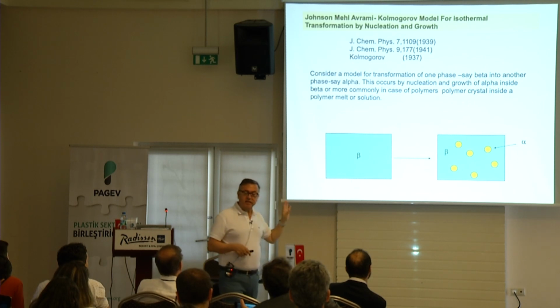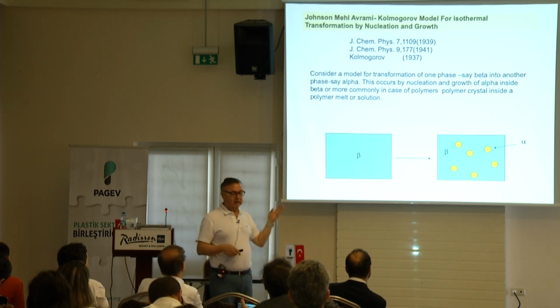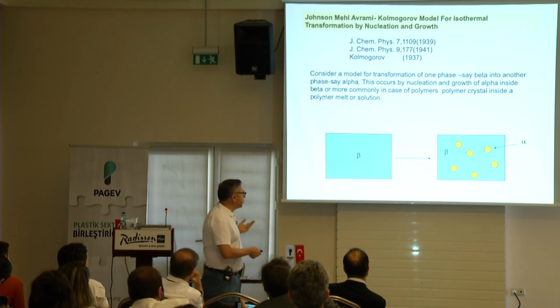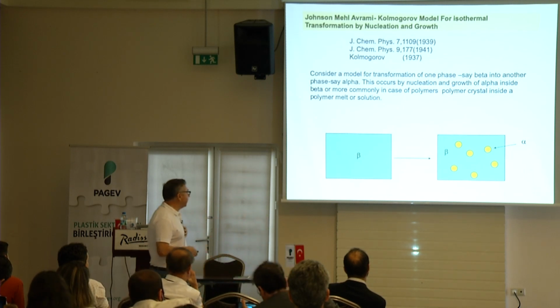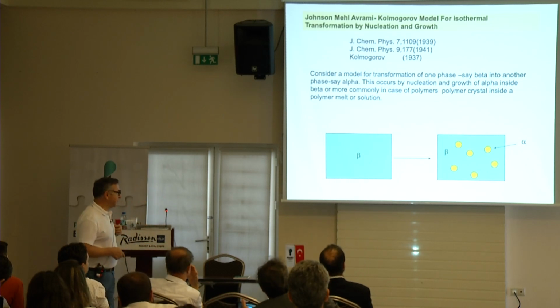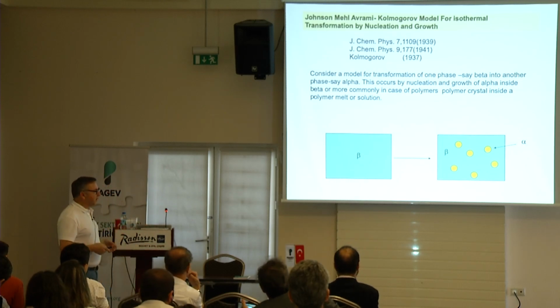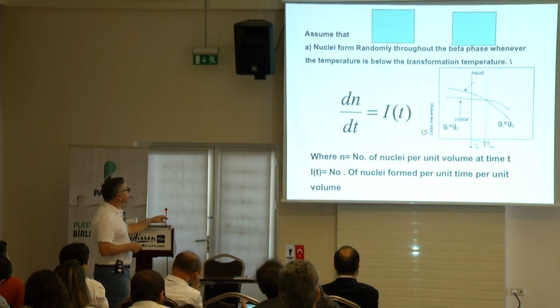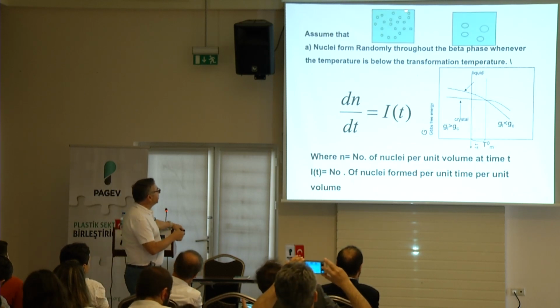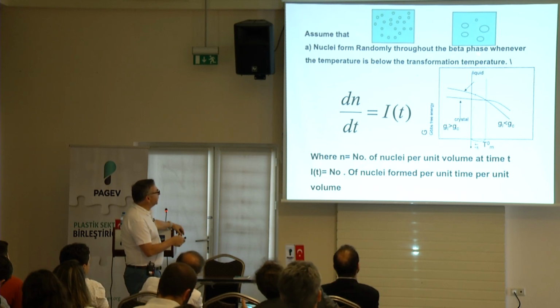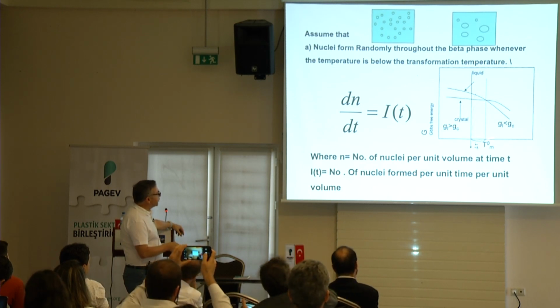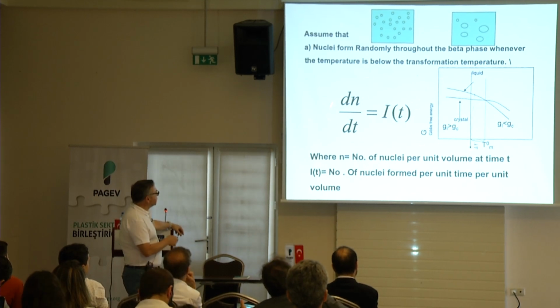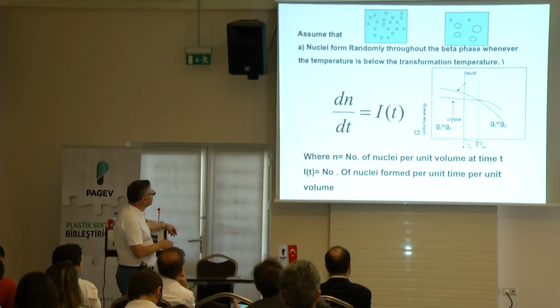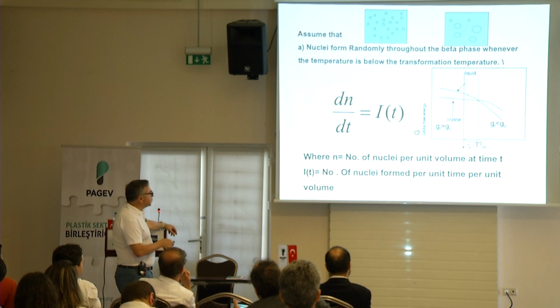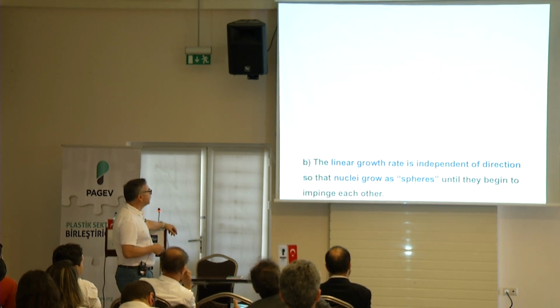They weren't thinking about polymers. They were talking about metal alloys or something, so beta phase growing inside, alpha phase growing inside the beta phase. Their assumption is that the growth is spherical, and so on. They basically assume that the nuclei form randomly, whenever the temperature is below the equilibrium melting temperature. So this is their expression of the nucleation rate, number of nuclei per volume, and how it changes with time. So it's all about this nucleation rate and how it controls it.